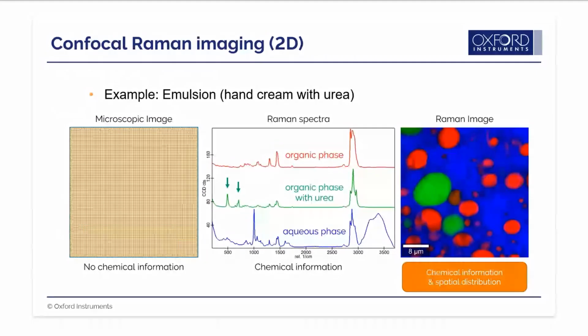Pixels in red color indicate positions where we have the organic phase without urea. Green pixels show the organic phase containing urea, and the blue pixels show the distribution of the aqueous phase, which forms the matrix in this emulsion.